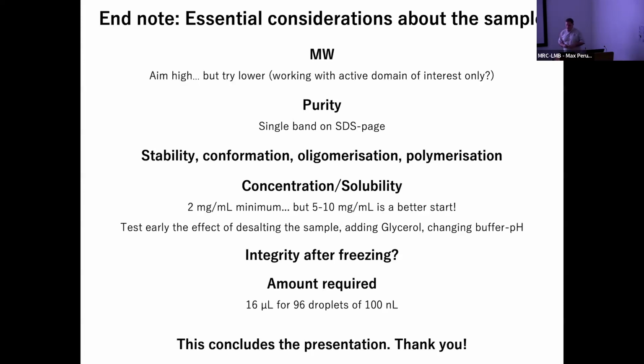Under that, there's no chance to crystallize it, even with conditions that are highly saturated, or it will be very rare that it does. But let's say that 5 to 10 mg per ml is a better start to have a chance to crystallize it. Now, if you didn't check the solubility of the sample, and in fact your sample, like the case I was talking about, is very stable, it may be able to reach 100, 200 mg per ml even, in which case, if you start at 5 mg per ml for your crystallization experiments, you're probably far off when you're thinking about reaching the supersaturation states. So you may want to look at the solubility of your sample. What I was doing before was sacrificing a part of my prep to push the concentration further and further and see what the limits were.